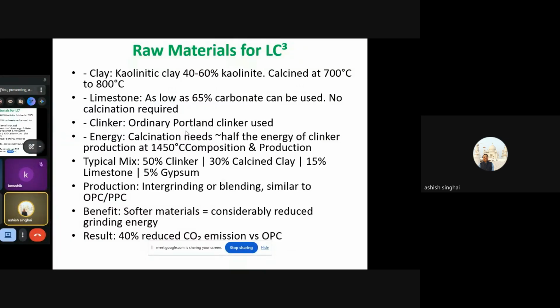What are the benefits? Softer materials considerably reduce grinding energy. As we know, since the temperature required is 50% less, these materials are very, very soft. The composition of kaolinite, which is basically calcined clay, is a very soft material. Grinding energy means the energy which goes to grind a material: the harder the material, the more energy will go; the softer the material, the less energy will go. So in this particular case, softer materials require considerably reduced grinding energy, which also contributes to our energy consumption, or what we call EBE, which I mentioned a couple of slides back. EBE is the embodied energy, which is the cumulative energy used in all the spheres. So the softer material requires a lesser amount of grinding energy. Talking about the result, 40% reduced carbon dioxide emission versus OPC.